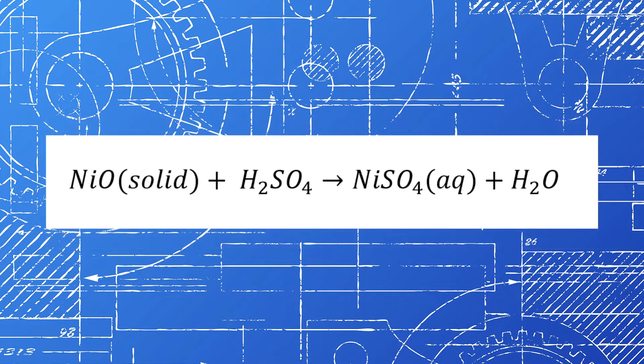So then, an additional reaction needs to take place prior to the battery acid reacting with the nickel. That is the reaction provided by the hydrogen peroxide. Hydrogen peroxide oxidizes the nickel with this reaction. The oxidized nickel then reacts with the sulfuric acid and follows this reaction. The two hydrogens in the sulfuric acid combine with the oxygen to create water as well as nickel and sulfate ions in solution.